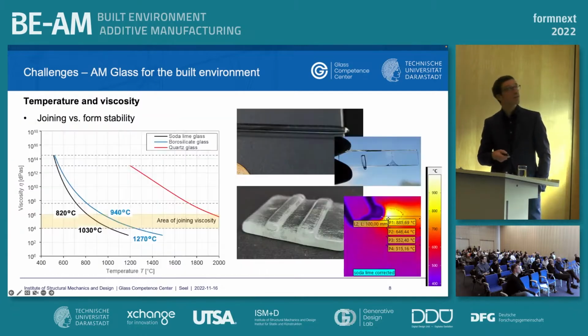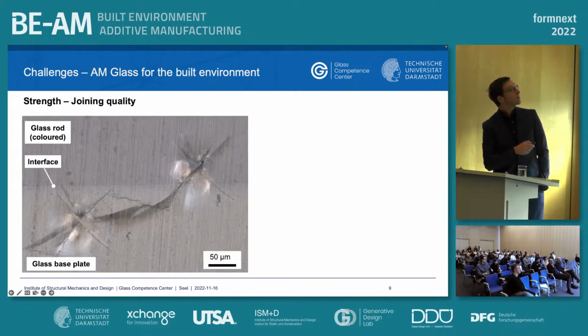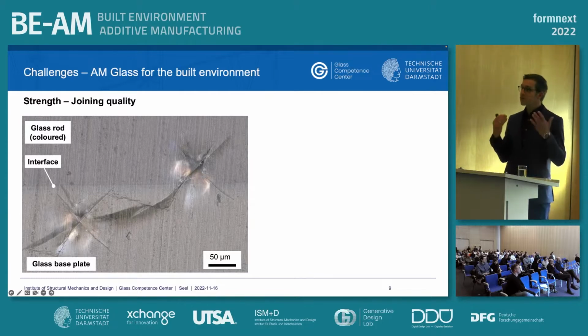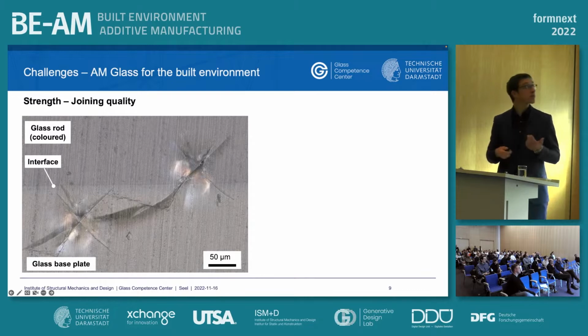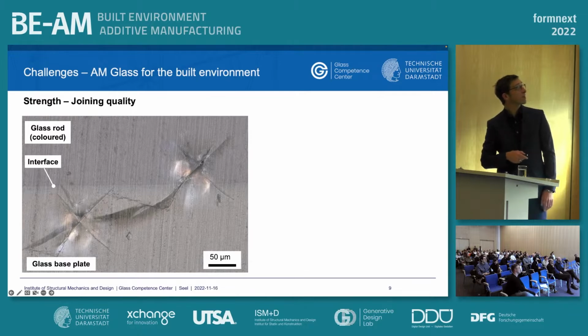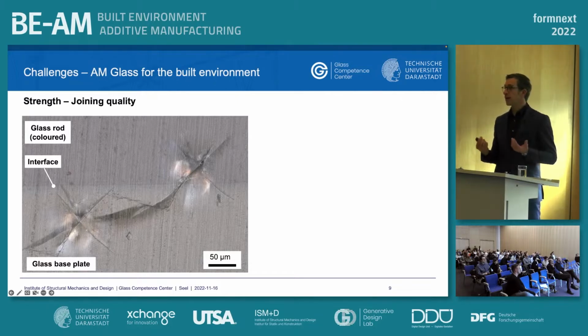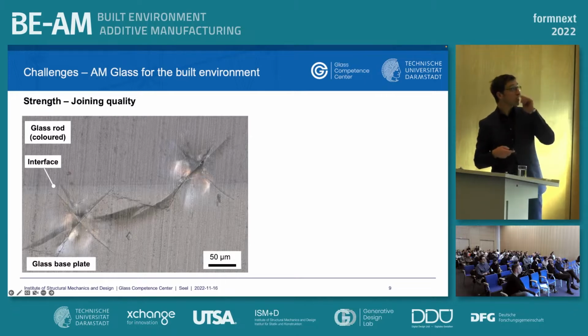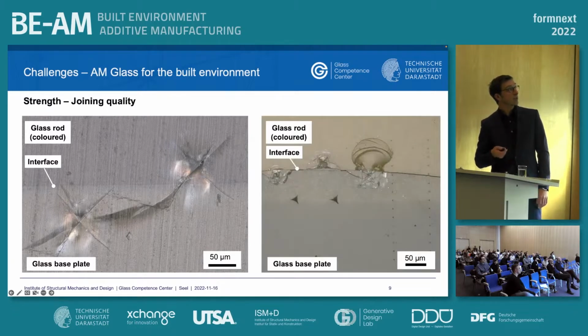And if you look at the strengths, on the next slides you will see a cross-section out of such a sample. Here you see the glass base plate, a colored glass rod, and the interface of both. Here you see the scale, and there is more or less no gap between. Also here you can transfer loads. We carried out an indentation test with a Vickers diamond, and there we create some cracks, and the crack goes through this interface, so you see, okay, here we can transfer loads. It's a homogeneous connection.